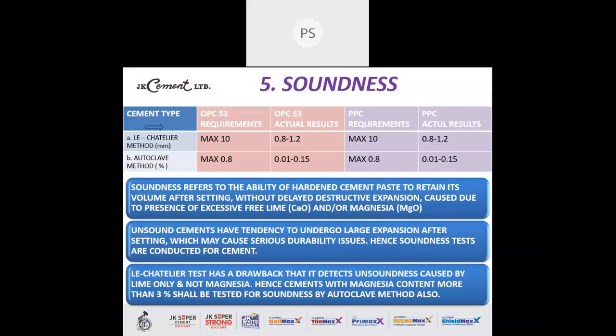Now what is soundness? Soundness refers to the ability of hardened cement paste to retain its volume after setting without the delayed destructive expansion caused due to the presence of excessive free lime, CaO, or periclase, and magnesia, MgO. Now if there is presence of excess free lime or magnesia, it will cause an expansion in the concrete, and there will be a delayed destructive expansion which will cause internal and external cracks on the concrete.